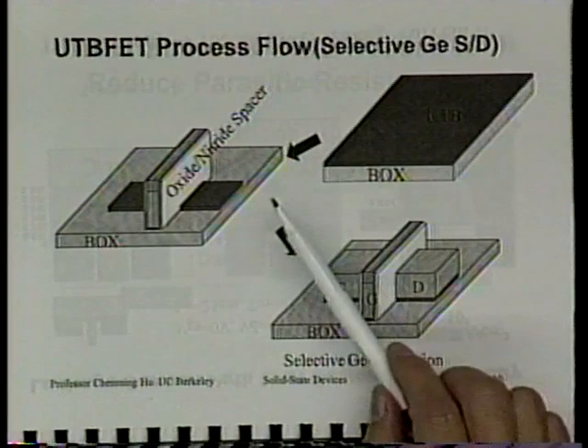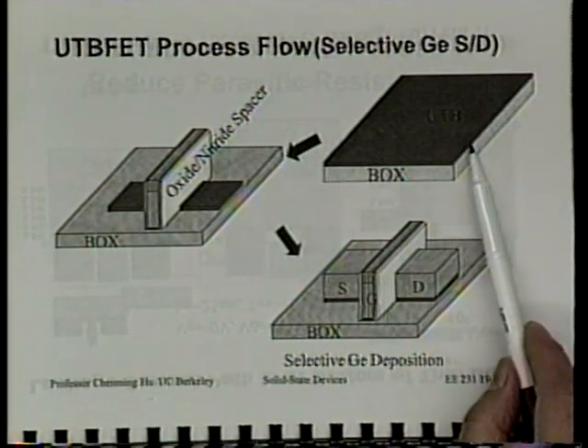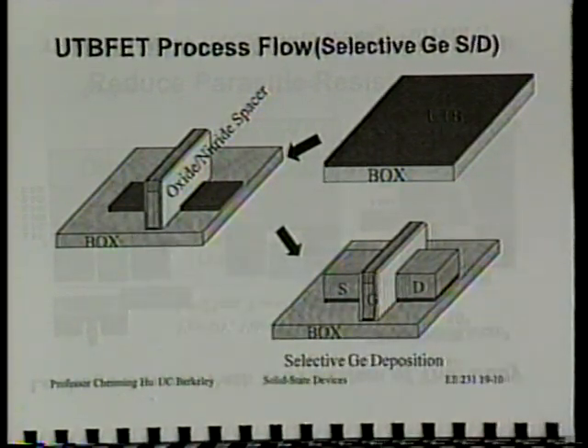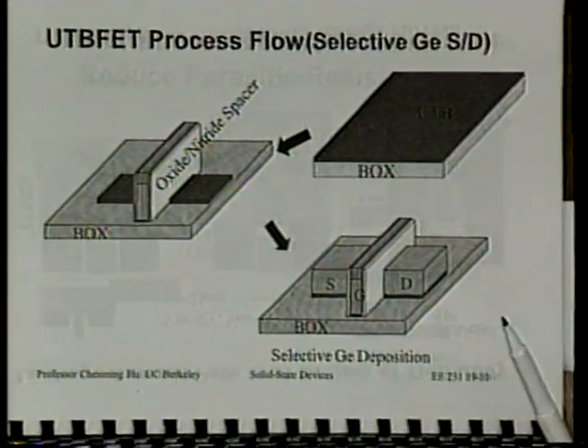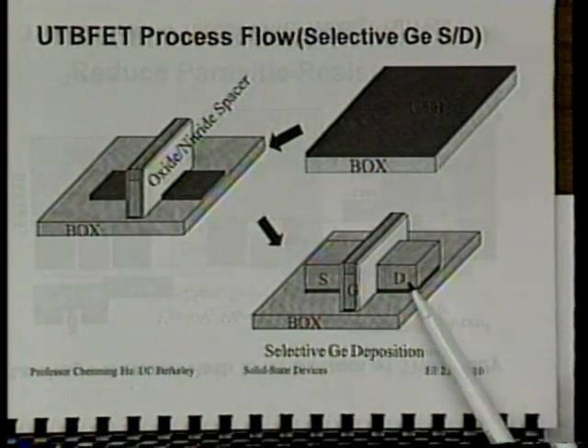So after we have reduced the SOI film to that thin thickness, we actually first pattern that. That will be the isolation, and then put down the gate and spacer as usual. Next, what Yang-Kyu Choi did is he put down selective germanium deposition to grow this thicker source and drain to reduce the series resistance. Now, normally people would do selective silicon deposition because that's actually a well-known process in the industry. But it turns out in our lab, it's easier for us to do selective germanium deposition.